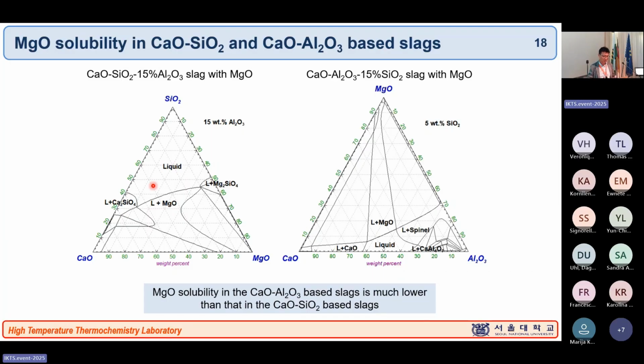So here you can see a wide range of liquid area, and this is the MgO saturation line. Okay, so this is the border. And again, CaO-Al2O3-MgO with 5% of SiO2. Here, this is the MgO saturation line. Why don't we have the tie line? Because the tie line only works in the ternary system with a specific domain, but here the tie line is not on this plane, so that's why we cannot plot the tie line.